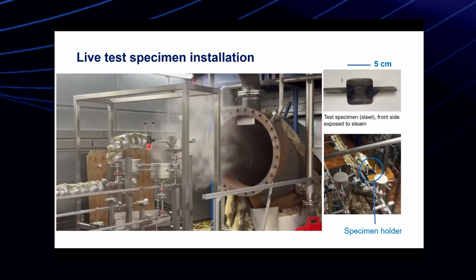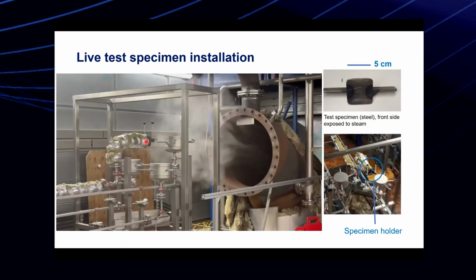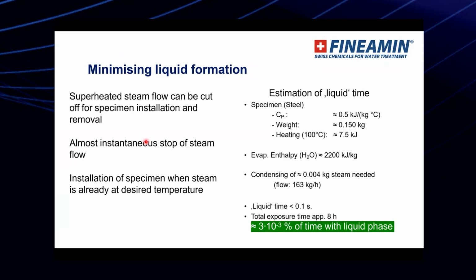So this is where the test specimen is, just right after the exit of the superheater, and the temperature is around 260 degrees Celsius. As I mentioned, it's important to minimize the liquid formation, of course, so the superheated steam flow can be cut for the specimen installation and removal. It can be done quite easily. It's quite modular in a sense. It's an almost instantaneous stop of steam flow and installation of the specimen where the steam is already at the desired temperature.